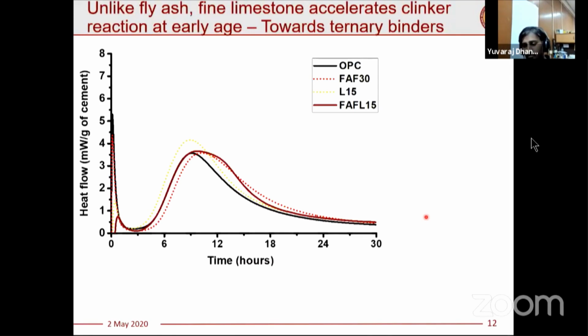So what is the impact when you start going towards co-substitution of SCMs? I give a hydration profile for the cement, for the fly ash system, which I talked about. So when you have just limestone in this system, you can see the acceleration in the clinker reaction. And when you start going for co-substitution, which is the brown solid line you can see here, you can bring the cement clinker phases to react similar to your plain Portland cement. By doing so, overall, the early age hydration characteristics are modified for the better.